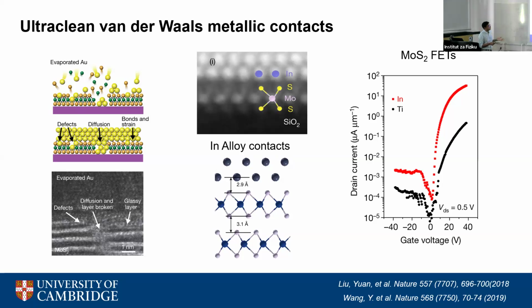This is a field effect transistor, which shows that when you apply the gate voltage, you can switch on the device. If you use a metal like titanium, which most people use, titanium forms a good contact because it has low work function. But the on current is much lower because you have a lot of defects, you lose a lot of carriers, and the carrier properties are degraded underneath the contact. But when you have these van der Waals contacts, you can really boost the on current and improve the device performance. Now, this paper was published in 2019, and we were still wondering why does indium form van der Waals contact? What is the difference?